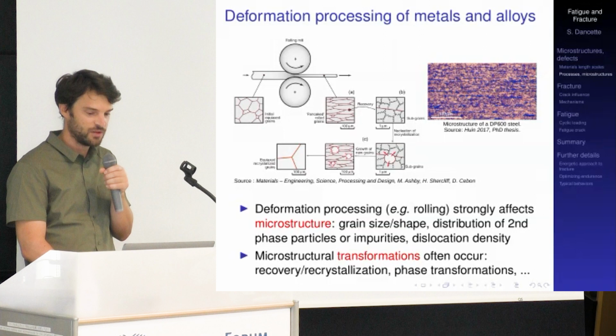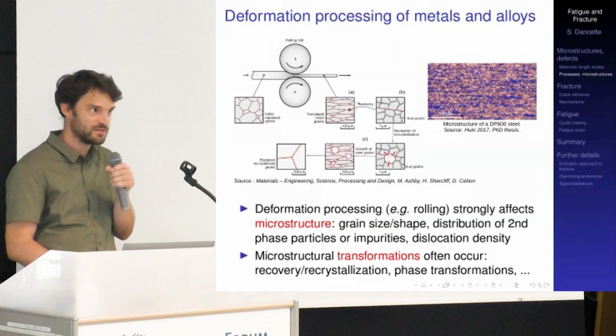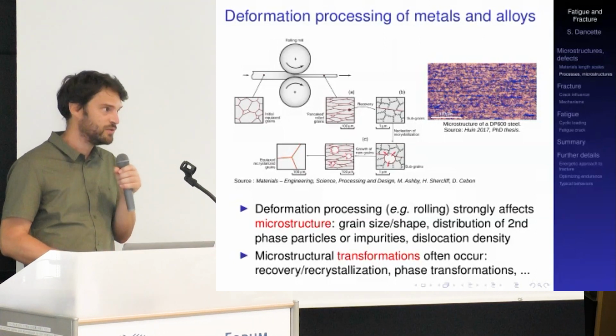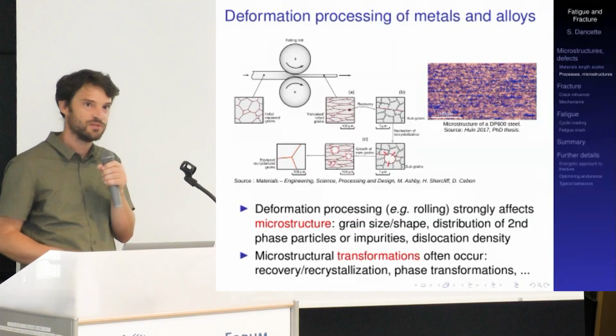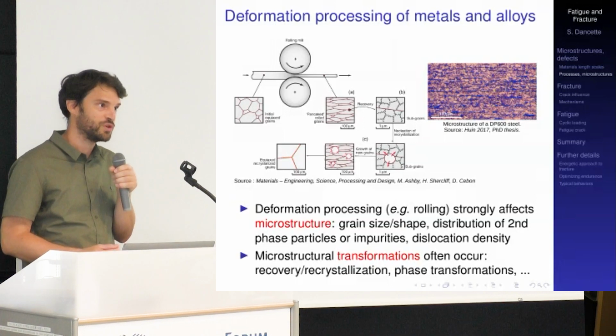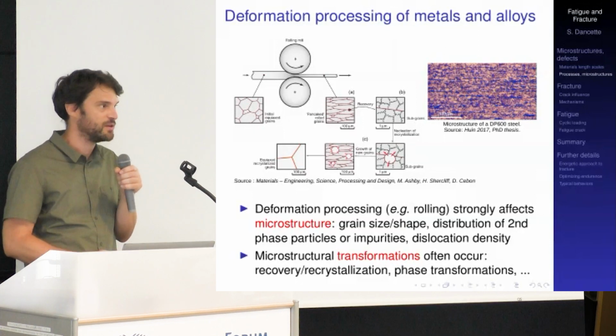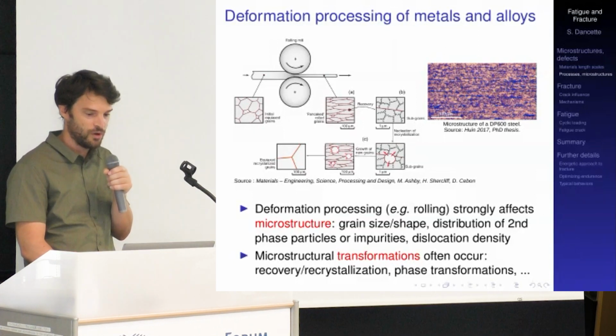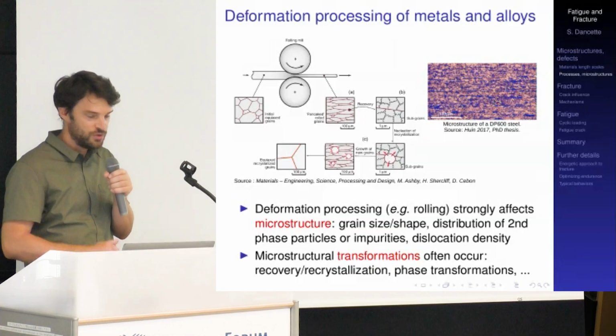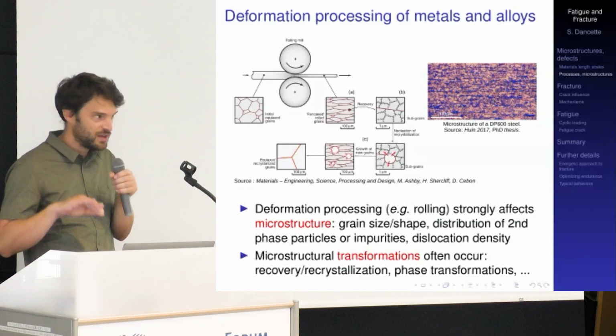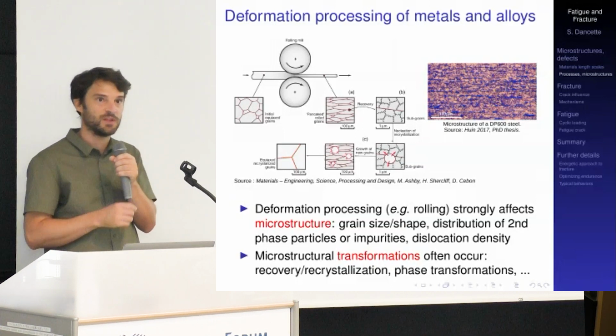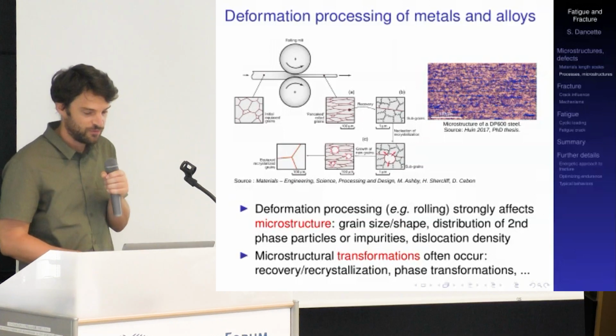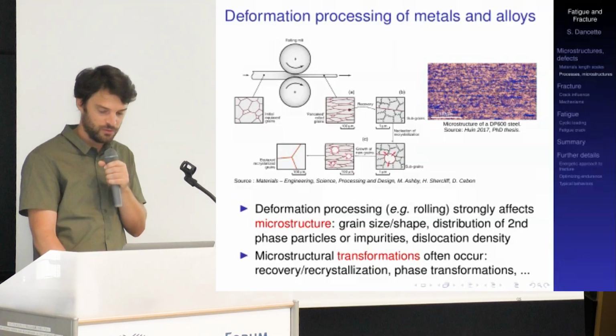But you can also start to note that when these martensite islands tend to be a little bit too much segregated or a little bit too much aligned in the same directions, then this will start to potentially cause some troubles in terms of the isotropy of the mechanical behavior. So already here we can see that the rolling process in that particular case induced some severe orientation, let's say, of the phases in the materials, and again, this will have some impact on fracture properties.